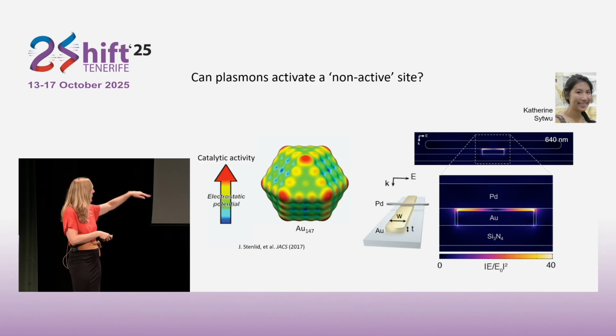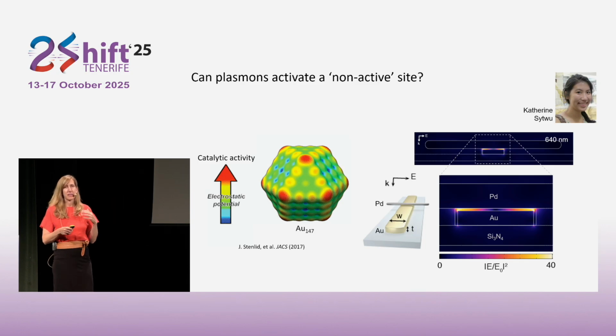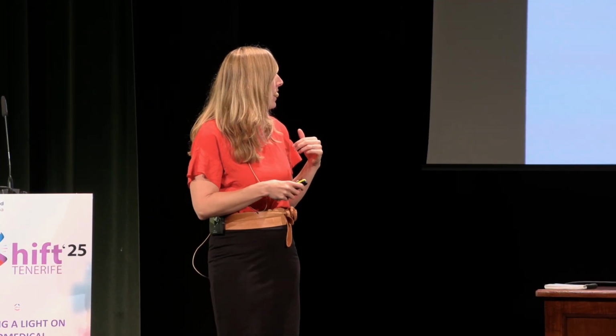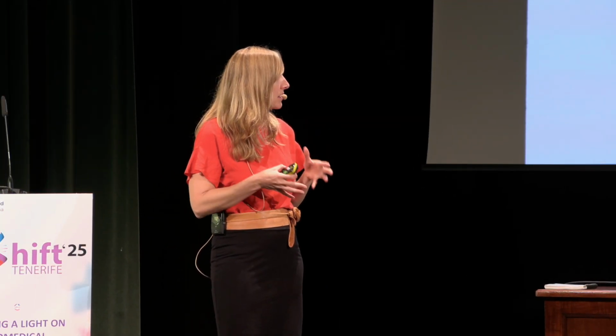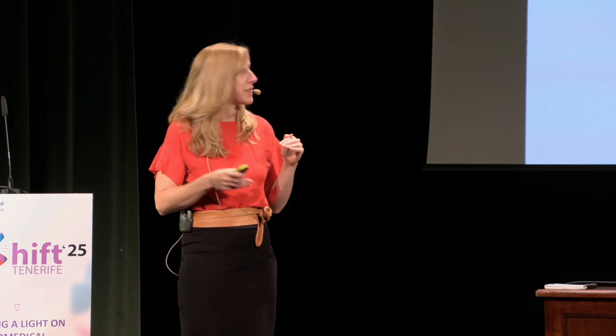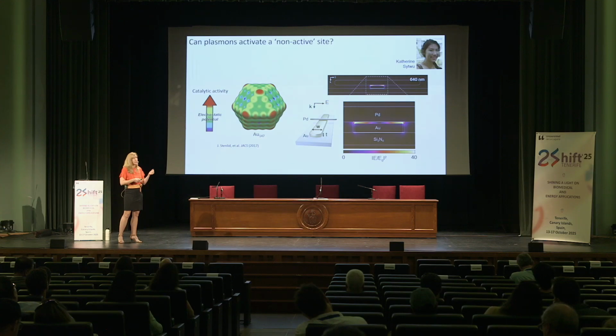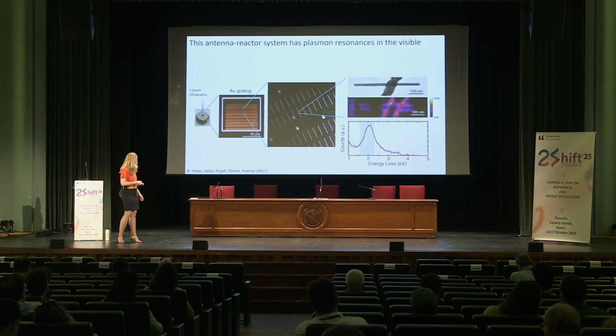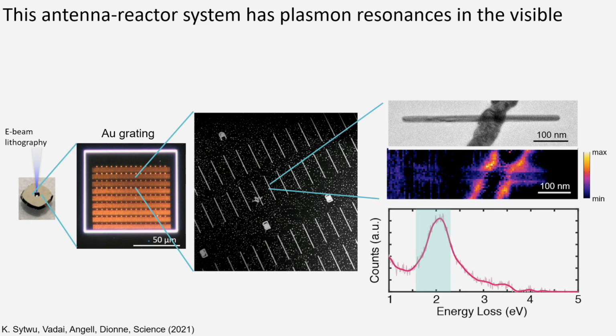So you can see here that we have an electromagnetic hotspot, basically a region of very strong confinement between the gold bar and the palladium nanorod. And we wanted to know if that region of strong electromagnetic confinement would change where the hydrogen was intercalating and deintercalating. So this is something that is called an antenna reactor system. So we have gold basically as a strong light absorber, and then we have palladium as the catalytically active nanoparticle.